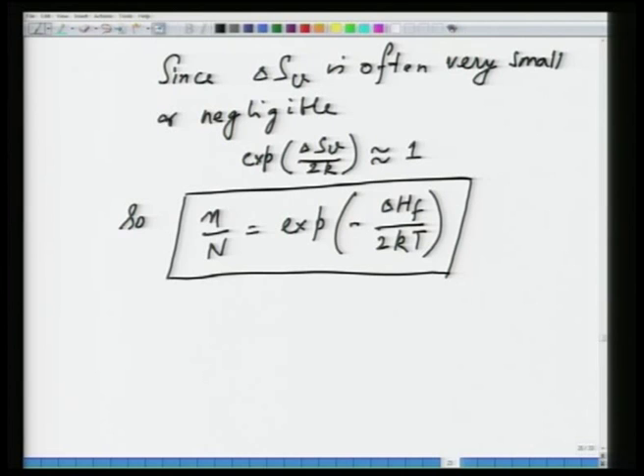Now, this expression tells you that n is an exponential function of temperature and enthalpy of formation. So, as temperature increases, n increases, and as delta Hf increases, n decreases. What you will see is that most of these ceramic materials have appreciable intrinsic defect concentration at higher temperatures. At lower temperatures, they do not contain a significantly larger number of defects. Similarly, delta Hf is the enthalpy of defect formation, which you can guess represents the ease of defect formation.